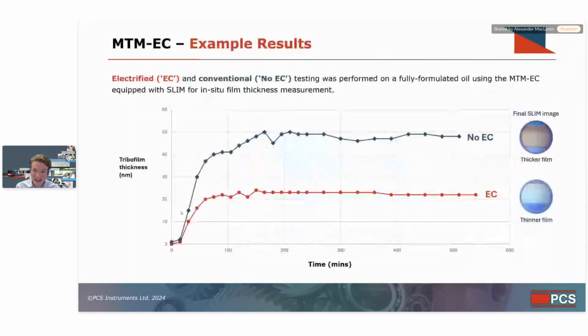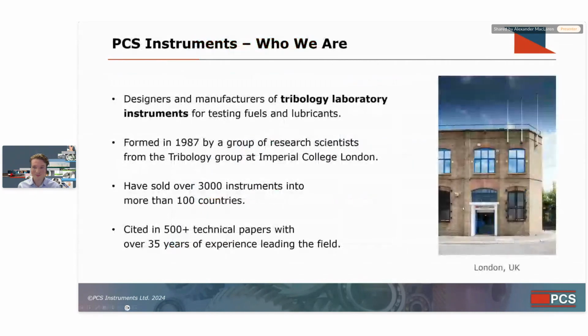I'm just going to briefly show you one example, combining some of those techniques. So this is the MTM-EC, like Amir showed, and a test that you might do, for instance, Amir showed that there's an effect on wear. I'm going to show there's an effect on tribofilm thickness. So here I've used SLIM to measure the tribofilm at different times during a test where we've rubbed two specimens against each other in the presence of a lubricant that contains an additive that forms a thick anti-wear film. So the non-electrified contact creates really quite thick films, while the electrified contact creates much thinner films under equivalent conditions. And this is perhaps one of the important things to know when you are designing a system where the contact might be electrified by stray fields.